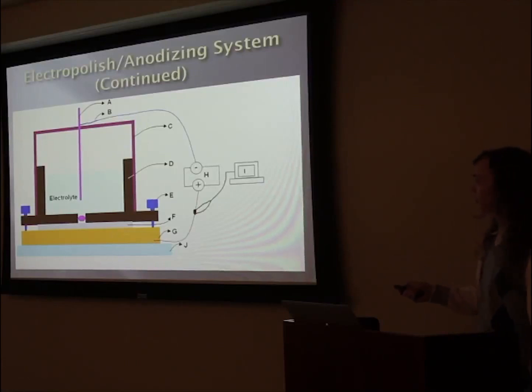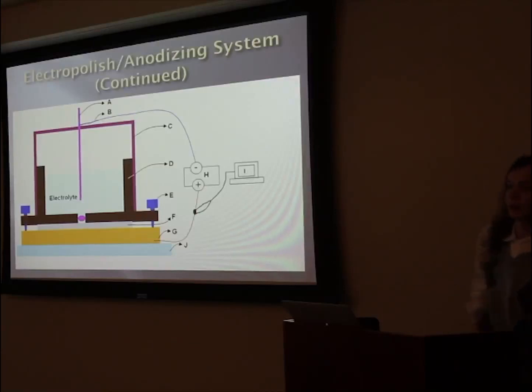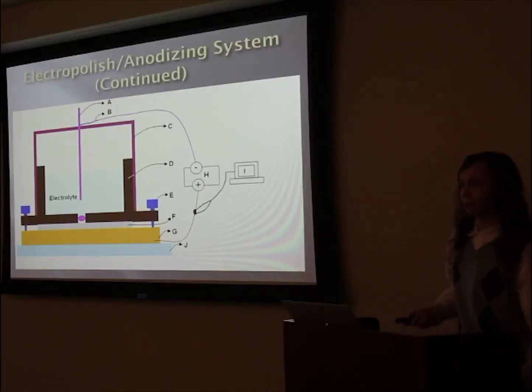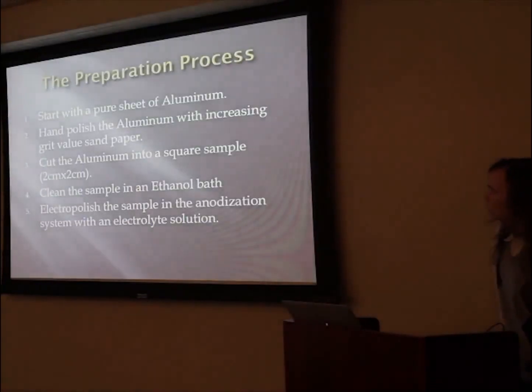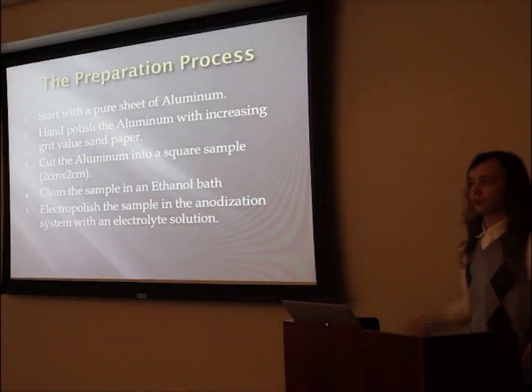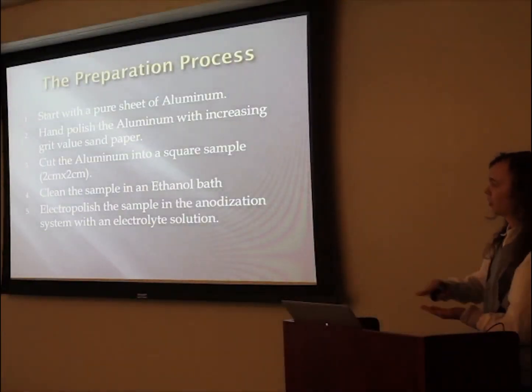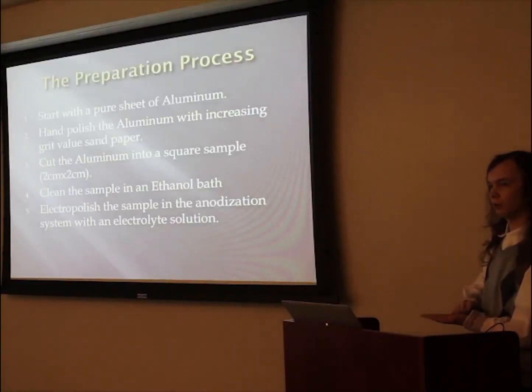So then you push a current through here, and we can measure this by putting a resistor alongside it in a circuit. You can measure the voltage across it, and that can give us meaningful data when we're actually going through this process. So the first thing you want to do is you start with a sheet of aluminum, you hand polish it, which makes that kind of dull surface that you saw before.